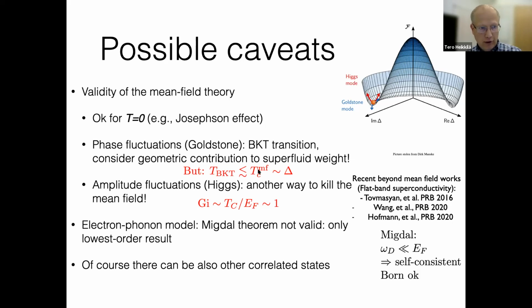Once you include the phase fluctuations, indeed you get this BKT transition. But actually, there's also the possibility of amplitude fluctuations, which is basically the Higgs mode that affects, let's say, the dynamics. And this is another way to kill the mean field.